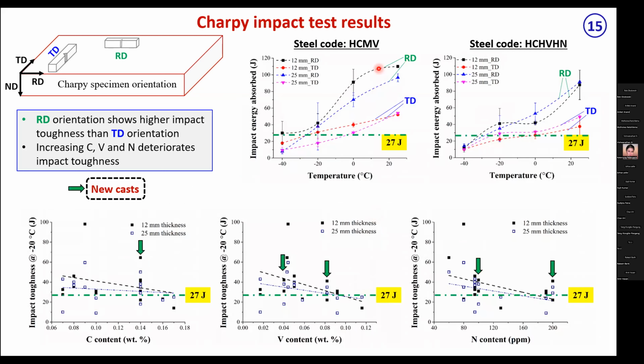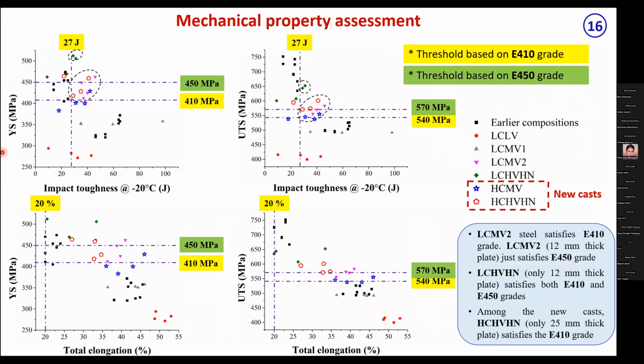So these are the transition curves for high carbon, medium vanadium. It's a sharper transition, whereas the high nitrogen vanadium steel has a more gradual transition. Overall, these are the properties, and these are the minimum required levels, and several data points are lying above the minimum required level. Here, we are plotting all the yield stress and impact toughness of whatever steel we melted under this project.